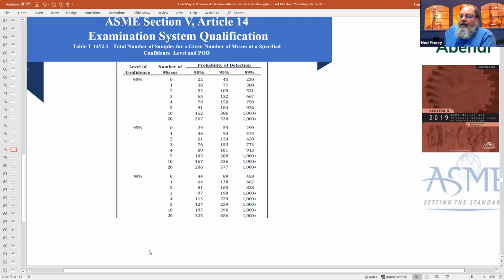So table T 1472.1 has level of confidence, the number of missed flaws, the probability of detection. It doesn't have the false call information, that's a separate function. But if you want a 90% level of confidence with a 90% probability of detection, then you can have 0 missed flaws, and you have to have at least 22 flaws in your sample set. If you want to allow the examiners to miss a flaw or 2 or 3, then you have to have a lot more specimens, flawed samples in your sample set.